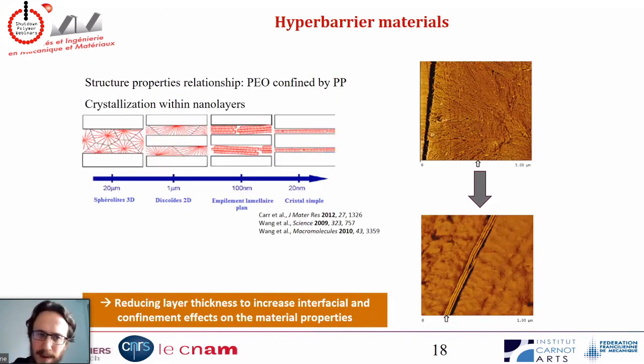Now, if I confine my spherulite, what will happen is that I will go from this relatively isotropic shape to something oriented in the direction of the thickness, so of the walls of my confiners. So if I go from microns to nanometers, then instead of having lamellas in every direction, I will have one lamella that is oriented perfectly in the direction of the wall.